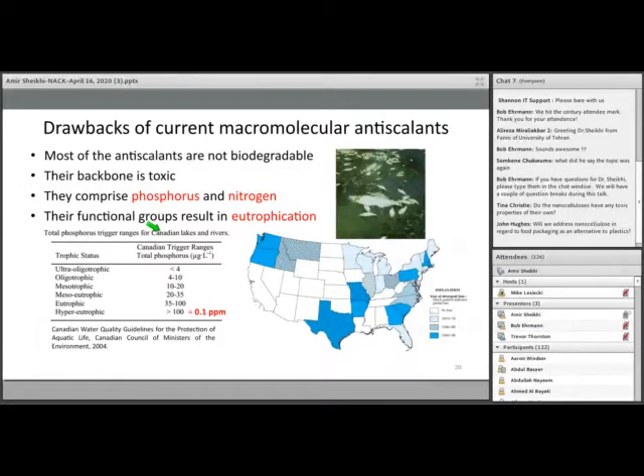So these macromolecular materials have some drawbacks despite their pretty good performance. They are typically non-biodegradable. Their backbone is sometimes toxic, and they are made of phosphorus and nitrogen based functional groups that are excellent nutrients. And when they are dumped in free water, they result in the so-called eutrophication process, which is the excessive growth of sea plants resulting in the elimination of fish due to preventing the diffusion of oxygen and sunlight into the water. You have seen this green water. So that is an environmental problem. The presence of only 0.1 ppm of phosphorus in water will label it hypereutrophic. And there are currently some regulations even against using phosphonated detergents, including the limitations in Pennsylvania.